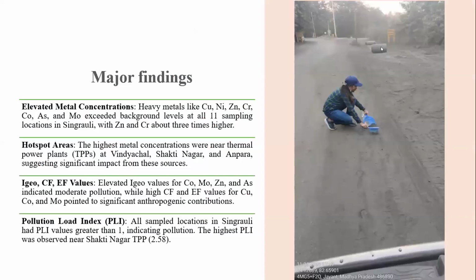Now the major findings of this experiment are that heavy metals like copper, nickel, zinc, chromium, cobalt, arsenic, and molybdenum exceed the background level at all 11 sampling locations in Singrauli, with zinc and chromium about 3 times higher. The hotspot areas with the highest metal concentration were near the thermal power plants at Vindhyachal, Shakti Nagar, and Anpara, suggesting significant impact from these sources.